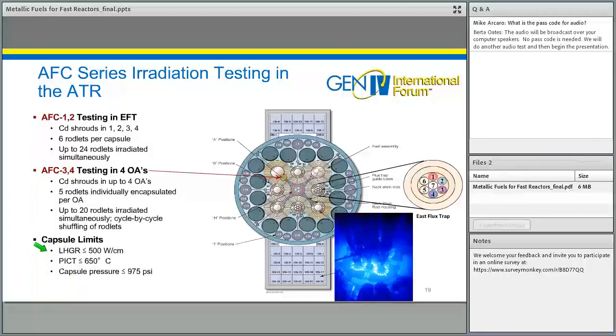it's a double encapsulated testing approach. So your miniature rodlet is then put inside a secondary steel capsule with a very small gas gap between the capsule and the cladding that's used to raise the temperature of the cladding up into the temperature range you'd really like it to be. With this testing approach, we've been able to test at linear powers up to about 500 watts per centimeter.